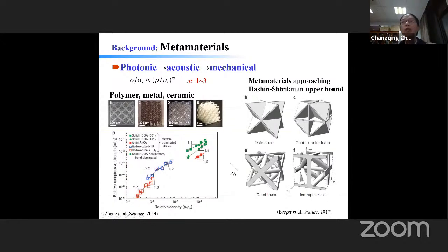And about 3 years ago, people were even able to produce mechanical metamaterial with stiffness approaching the theoretical Hashin-Shtrikman upper bound. That means it actually approaches the limit. We know from the Hashin-Shtrikman bound theory that you are not able to get material with stiffness higher than the bound. So this kind of material is very promising. In addition, we find this kind of material is elastically isotropic, which is another property people are very interested in.